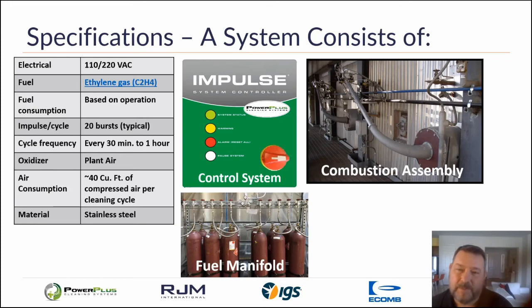Typically, there's a 1/2-inch supply line for gas and a 1-inch supply line for compressed air. We do use plant air. We do not require instrument air. And then a gas rack or fuel manifold is required at ground level, and multiple bottles would be manifolded into a single supply line. Typical consumption of gas is obviously based on the operation that is programmed, but most generally anything that is run at 20 impulses every 30 minutes would go through a 30-pound bottle of ethylene about once every 10 or 12 days. And each cleaning cycle, a 30-second cleaning cycle, would consume about 40 cubic feet of compressed air.